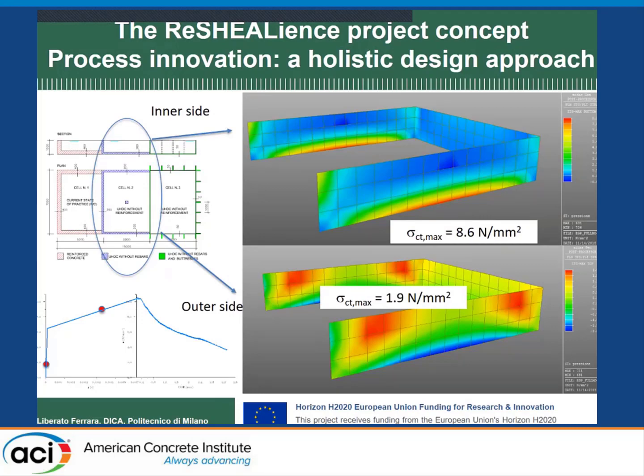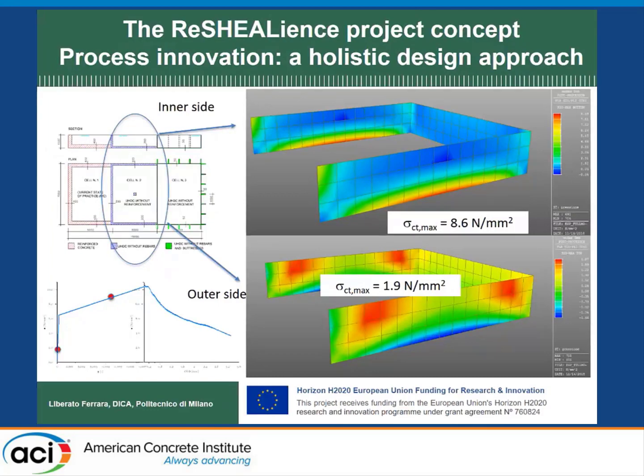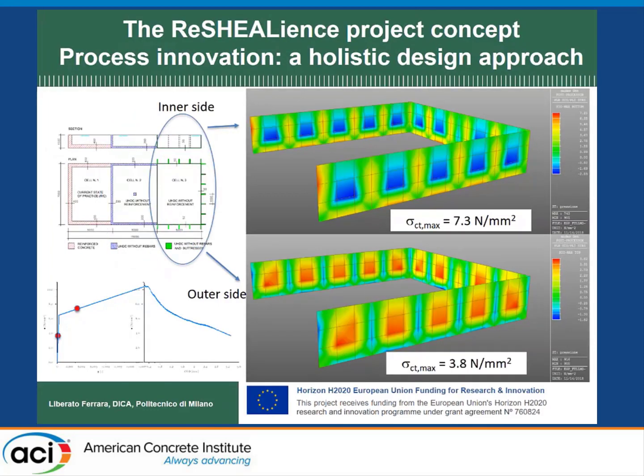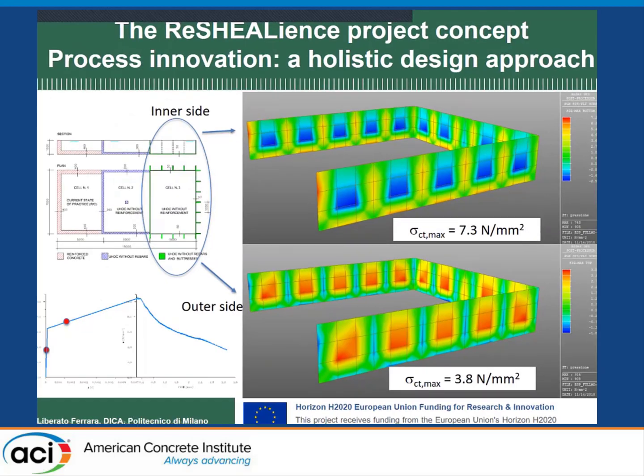And we also provided a partially precast solution, in the sense that we precast 1.5 meter wide square slabs, only 3 centimeters thick. And then we installed them and cast in place some columns or buttresses. And you can see here also some kind of optimization of the stress level, because on both sides of the slab, the material works at more comparable levels.